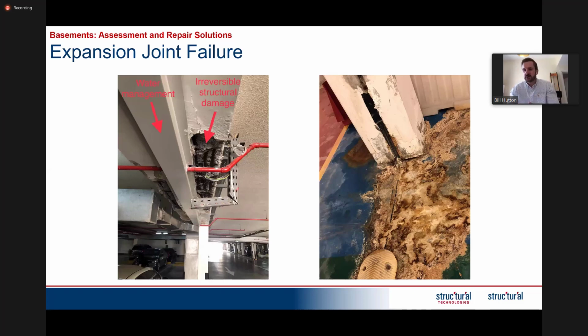But what they've actually done is this is at the expense of sacrificing the structure. So having this water management system in place and allowing this water to continuously seep through this joint has meant that over time, even though concrete's a hard material, it's actually like a sponge. So all of this water has been absorbed into the concrete. The water evaporates, the salt is deposited behind, and that eventually causes corrosion of the steel, which you can see here. A photograph on the right-hand side shows a failed expansion joint in a slab.